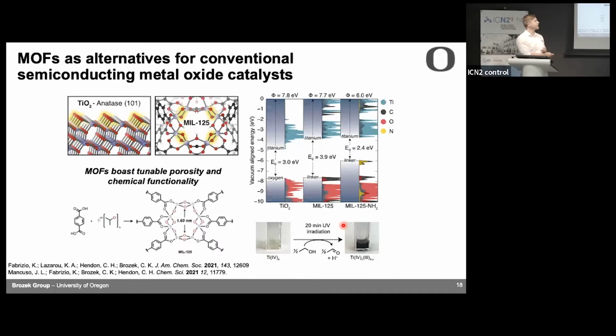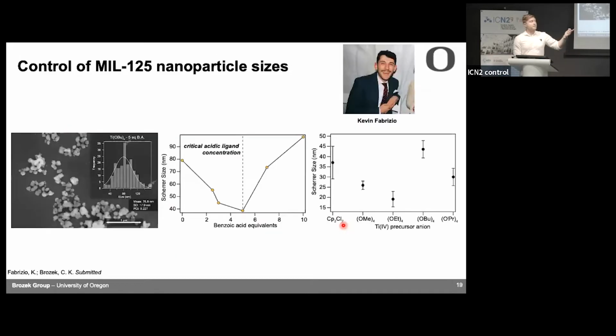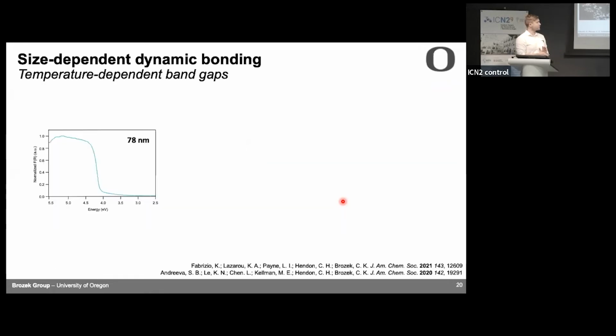That was the idea. To do this, we needed to make this as nanoparticles, which we were able to do. We can control their size. By controlling the amount of modulator equivalents, we can get that U-shaped seesaw relationship. The titanium precursor that we use also controls the size. We think the stronger the titanium-ligand bonds, the lower the concentration of titanium in the solution. So all this is nice. We can make these as particles of different sizes.